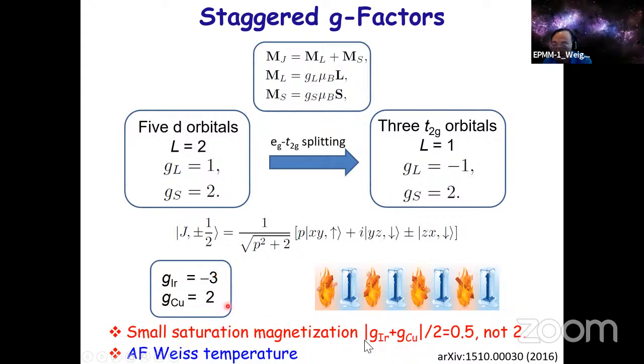That's the reason why it's a ferromagnet, but its saturation magnetization moment is very small. Also, if you apply a uniform magnetic field on a ferromagnet, it will actually introduce antiferromagnetic ordering of the spin and pseudo spins. So this will generate some strange state, like on the iridium side, it is fully frozen, but on the copper side, it becomes fully random.